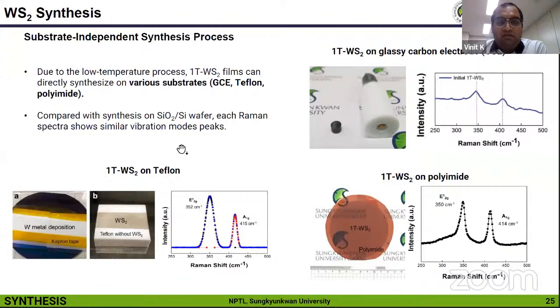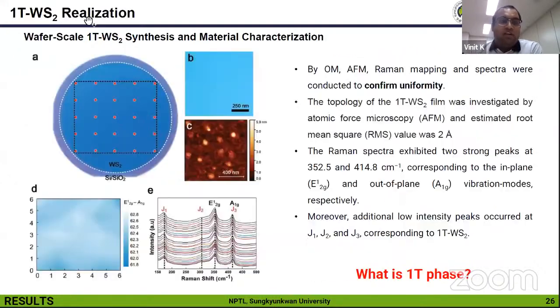There are many uses for this process. We can utilize this process on various substrates, as shown in this figure. We can use this WS2 on a glassy carbon electrode, which we utilize for our electrochemical application, as well as directly synthesize on Teflon, and on polyimide, which is a flexible substrate, along with silicon oxide. Here, as shown in this figure, we synthesized wafer scale WS2.